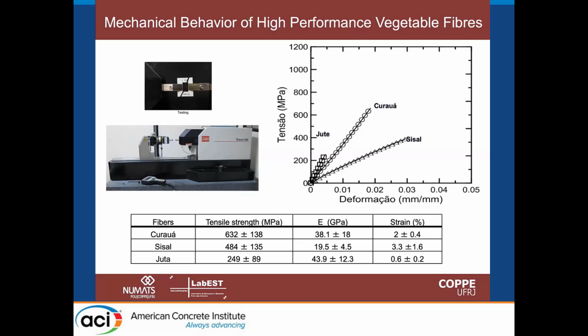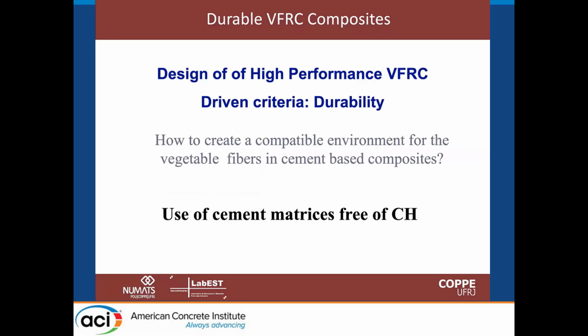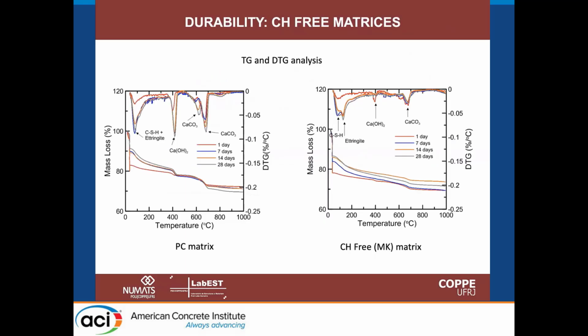These fibers, of course, need to be designed properly. We need to think about durability. And one big issue is the use of CH-free matrices. So the matrix must be free of calcium hydroxide. To do that, we normally use pozzolanic materials, like metakaolin, husk ash, or silica fume.